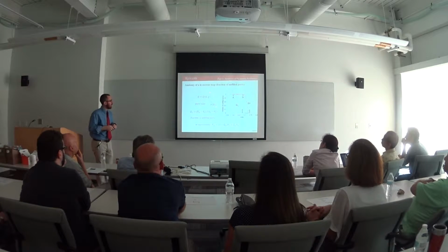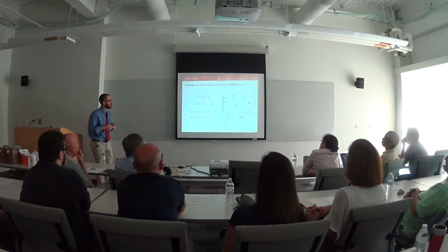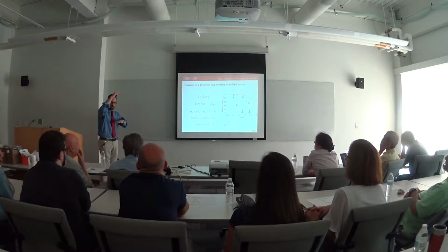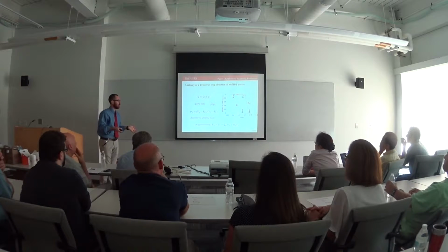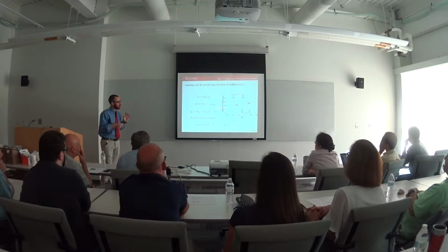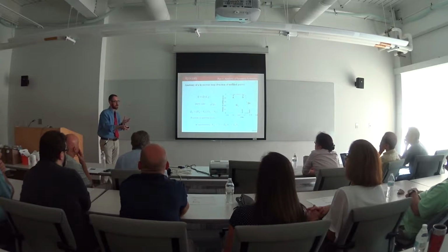So we can also define something called the fraction of unfilled pores, which is basically the inverse of our adsorption isotherm. So it's the difference between our adsorption isotherm and the surface isotherm normalized by the total difference between those two curves. And when we apply this equation to both curves, we get something that looks like an inverse hysteresis loop. And so the main part of this entire chapter is being able to describe theoretically what these two curves look like for both the boundary hysteresis curve and also the scanning curves. And this differs based on porous material.